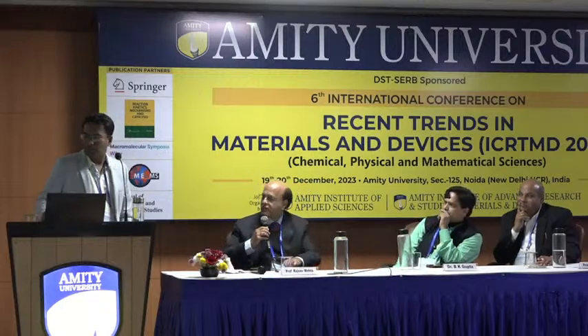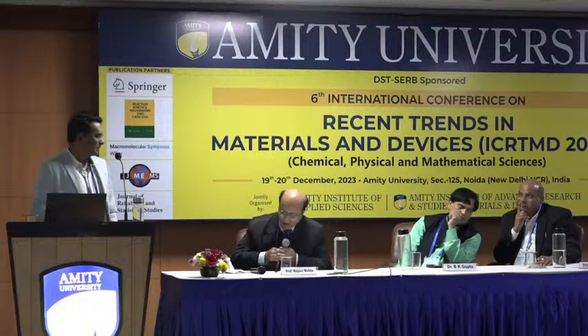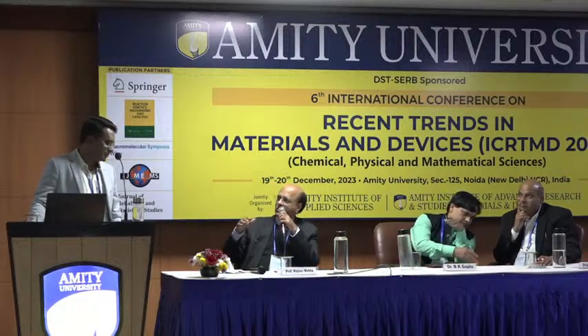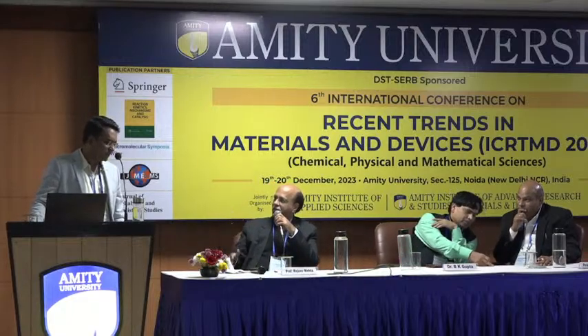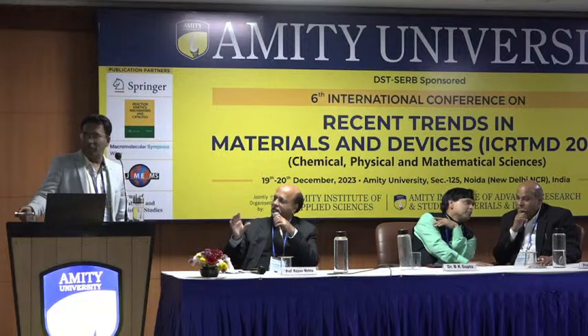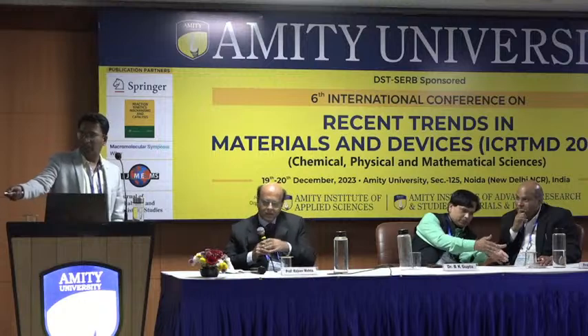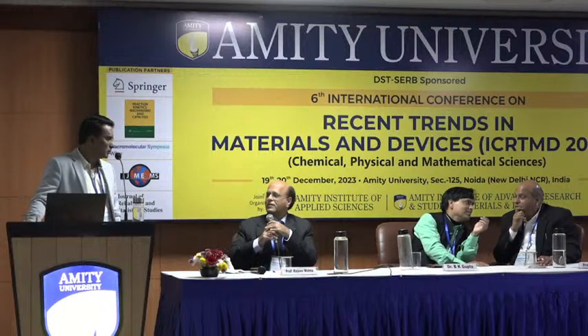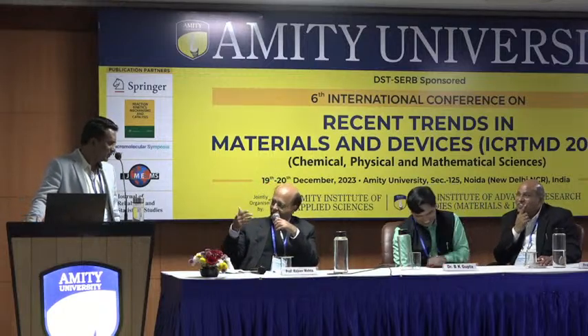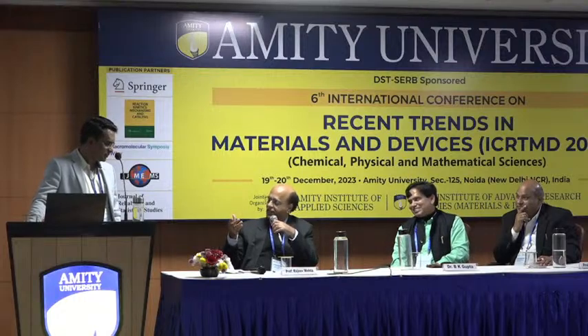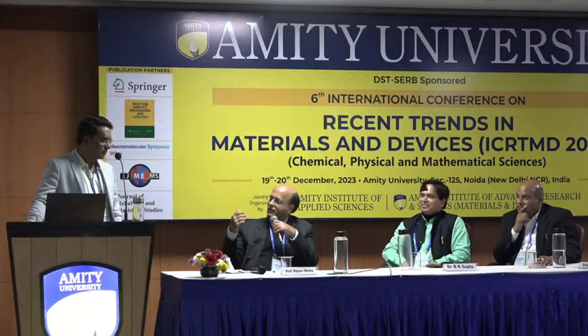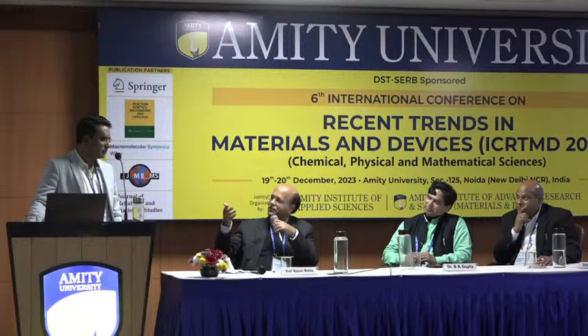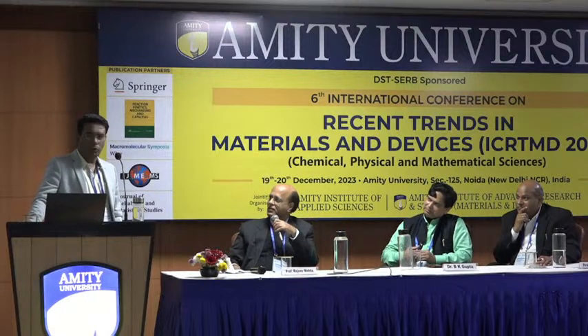Sir, I have one small question. Yes, please. You had shown that you used the catalyst 11-12 times without much drop in the activity. Yeah, there is a little decay in the activity. But since you are claiming it's an adsorption-based mechanism, did you try to treat the catalyst after a few runs in any way? No, for this work we did not do anything.